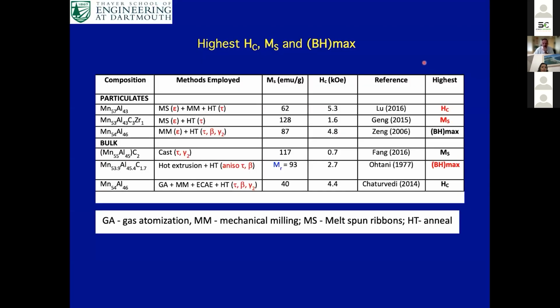This actually summarizes the best coercivity, saturation magnetization, and energy product values for both particulates and bulk material. And again, you can see the best value for the saturation magnetization is actually in a particulate material, as is the best value for the coercivity. But actually, the highest value for BHmax is actually in a bulk material.